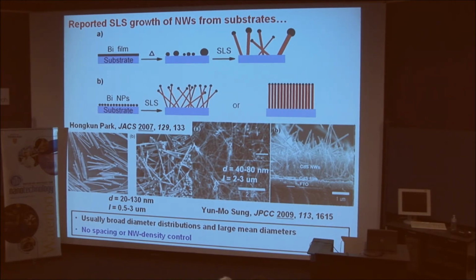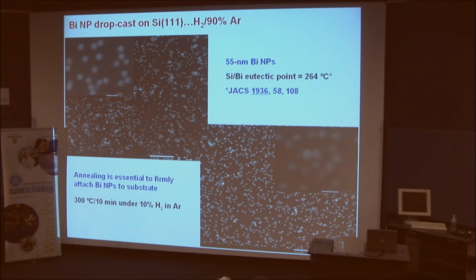So let's see what we can do. Well, the first thing we do is we drop cast the bismuth nanoparticles on the substrate. These are rather larger ones because they made a nice SEM image that you can see. And it's important that after depositing them, we actually anneal these at an intermediate temperature. What temperature do we anneal these at? Well, in this case, about 300, because that affixes the catalyst particles to the substrate.